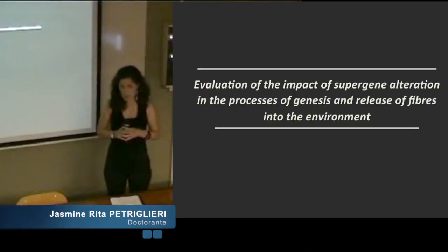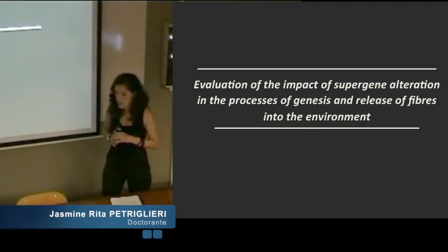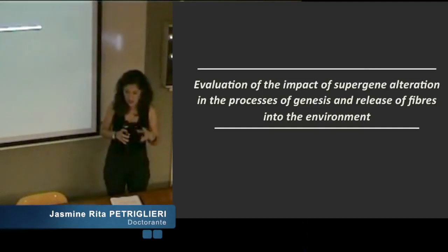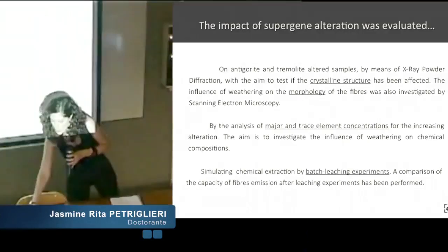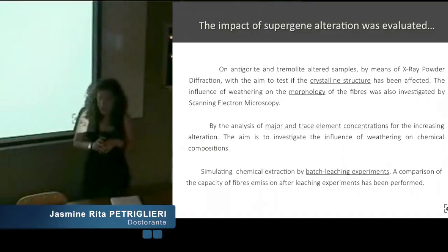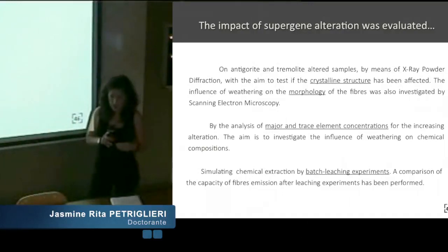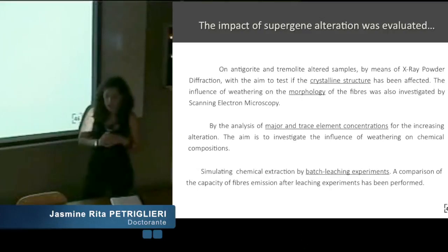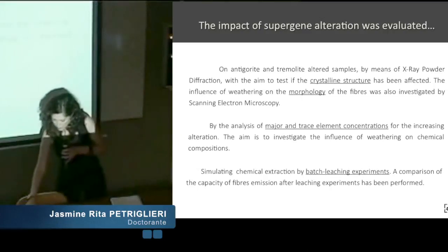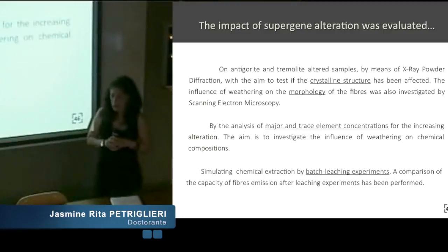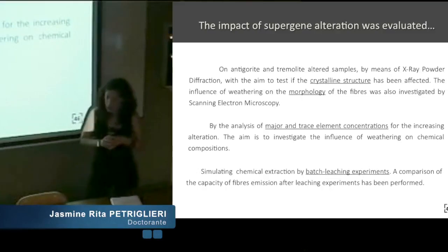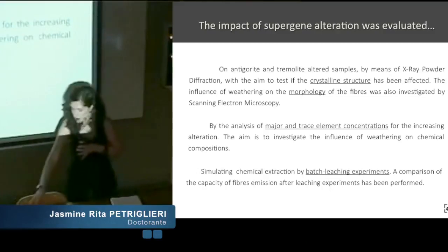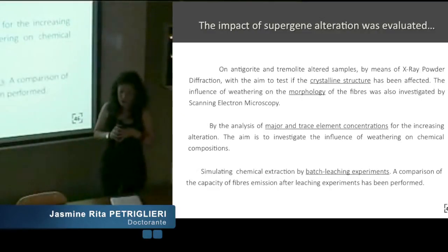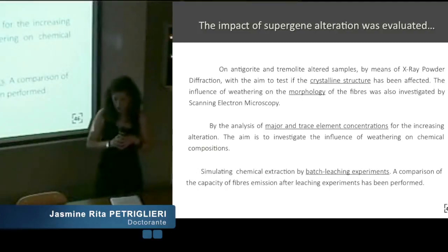The second part of this presentation is dedicated to the evaluation of the impact of supergene alteration in the processes of genesis and emission of fibers into the environment. The impact of supergene alteration was evaluated on the antigorite and tremolite altered samples by means of X-ray powder diffraction and scanning electron microscopy to study any possible modification on crystalline structure and on morphology. A study of the major and trace element concentrations was carried out in order to investigate the influence of weathering on chemical composition. So, two simulating chemical extractions by batch leaching experiments were performed, and a comparison of the capacity of fiber emission after leaching was made.